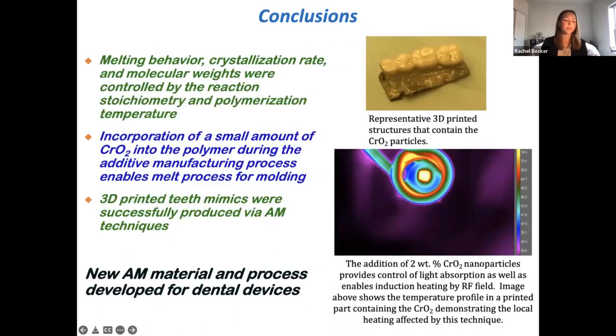So in conclusion, we use the thiol-ene polymerization to create a material that can be 3D printed, and we can also adjust the melting behavior, crystallization rate, and molecular weight by adjusting reaction stoichiometry and polymerization. And then by including chromium oxide nanoparticles, we're able to heat this material and melt it away by induction heating. And basically the main idea is that you could use this material system to cast mold and process dental devices. So thank you for listening to my presentation, and I can take any questions at this time.